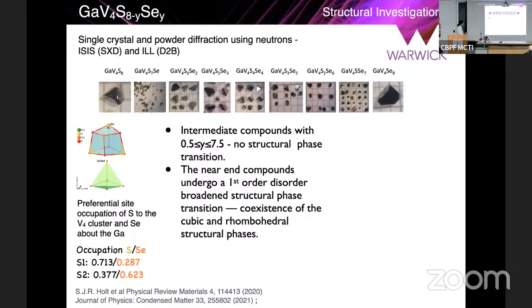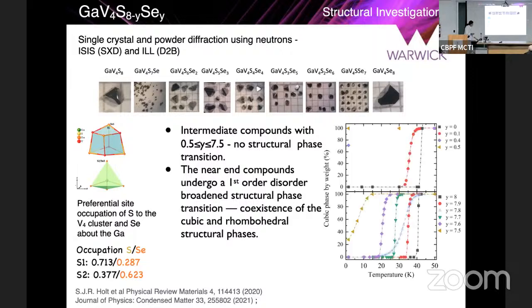Very close to the selenium-8 and the sulfur-8, not in such a large step, but in very, very small steps. And what we find is, I'm sorry, there's a delay between me pressing this and the picture actually showing up. So we are also able to characterize the gallium vanadium 4 tetrahedra that I spoke about. And we actually know for all of these materials where the selenium sits and where the sulfur sits as we go from one end to the other. And we find that there's a preferential occupation of the sulfur on the vanadium 4 cluster and the selenium sits around the gallium. So we can pinpoint exactly where all these atoms sit.